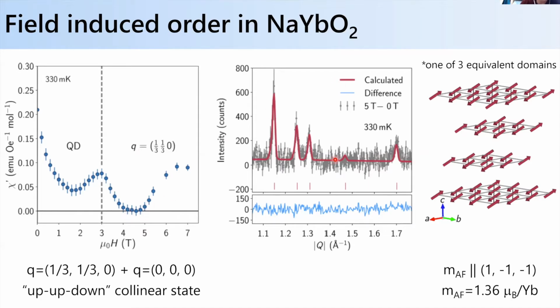And we can solve the magnetic structure. It turns out that the solution that works best has a propagation vector. It's a 2q structure, which is a third 0 plus a q equals 0 component. And this maps to the up-up-down collinear state that I mentioned earlier. So we apply a magnetic field, and the best solution we get is an induced up-up-down state where the ordered moment is about 1.4 μB per ytterbium ion. And there are 3 magnetic domains that should occur. I've just shown you the orientation for one of them, okay?